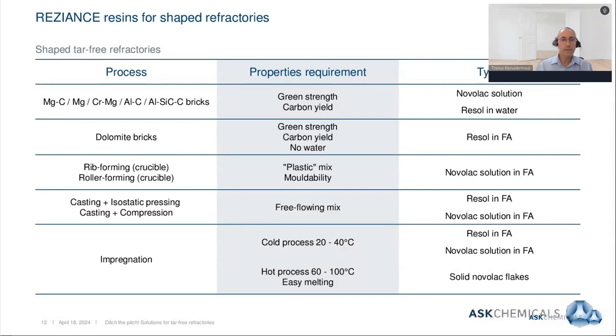And lastly, in the case of the impregnation process, for the purpose of reduction of porosity in shaped refractories, whether you use the cold process or the warm process. In the case of cold process, you would consider resols or Novolacs in furfural alcohol. In other words, liquid material at ambient temperature. Or in the case of warm process, your consideration would be a solid Novolac with the prerequisite of having a low softening point, a low melt point, for the sake of easy melting and having a low melt viscosity. Next slide, please.